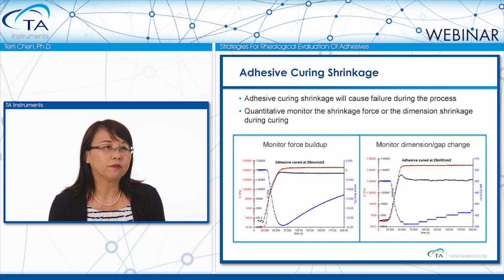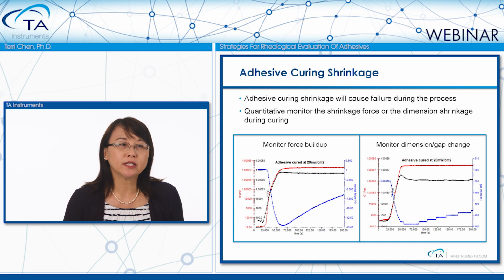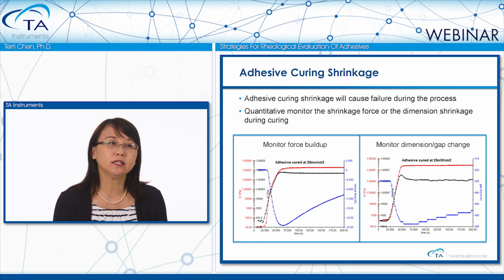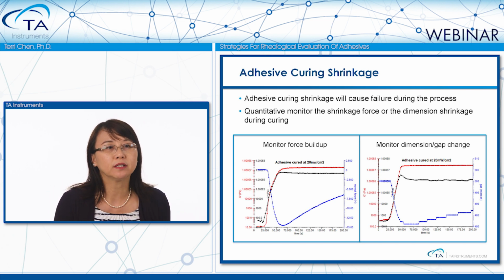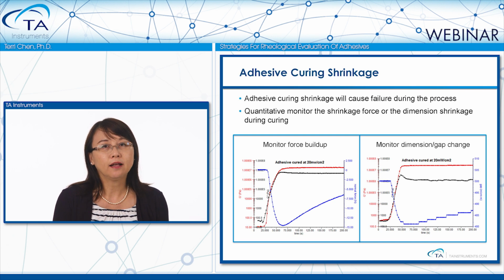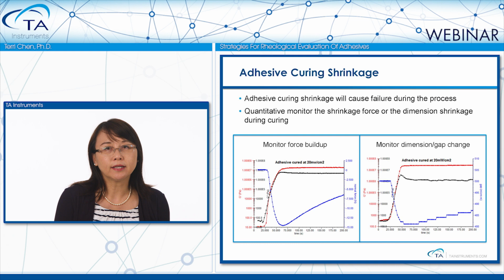As we can see from the figure on the left side of this slide, if we fix the measurement gap during the measurement, we can quantitatively monitor the axial force buildup during curing, which is shown in the blue curve. For this particular sample, the force increased up to almost 15 Newton across a 20 millimeter diameter plate. And then after the curing is completed, the force slowly relaxed over time.